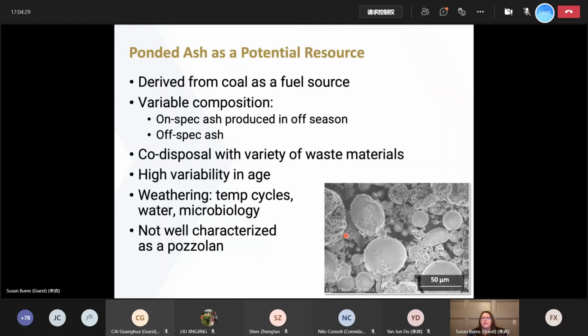So let's think about the ponded ash, because that tends to be higher in organic carbon content than some of our other ashes that we deal with. We know that it is generally derived from coal as a fuel source, typically 100% coal. But we do know that it has variable composition. In some cases, ponded ash might be ash that was on specification, but it was produced in the winter when construction was slow and we didn't have a use for it. Or it could be ash that was produced off specification, so its organic content was too high to use in concrete. We also know these ashes are often co-disposed with a variety of waste materials, and they have high variability in their ages. They've been weathered, they're wet, they've had microbial activity, and historically they're not very well characterized for their pozzolanic capability.